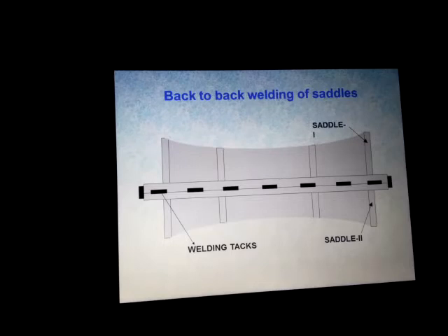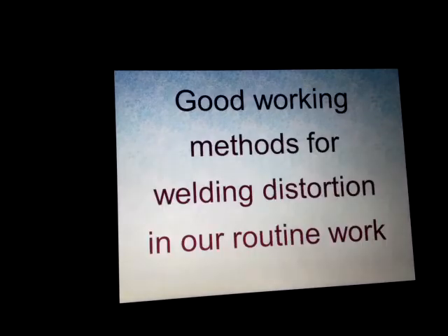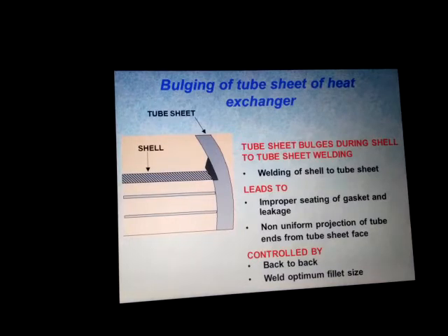Back-to-back welding of a saddle is a good working method for welding distortion in our routine work. Tube sheet bulges during shell to tube sheet welding. Welding of shell to tube sheet leads to improper seating of the gasket and leakage. Non-uniform projection of the tube end at the tube sheet face is controlled by back-to-back welding and optimum fillet size.